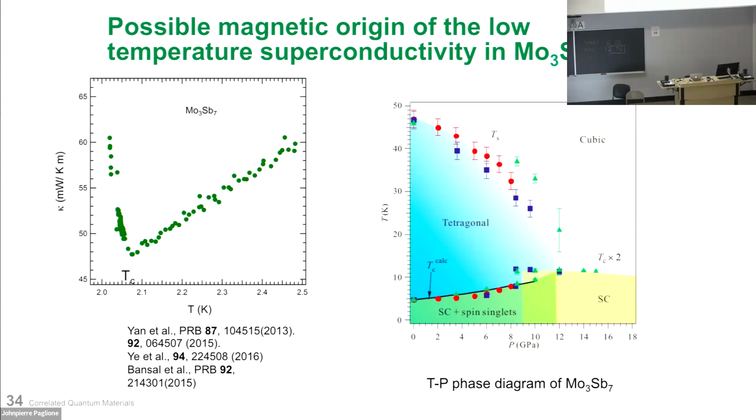So we thought that this was very interesting, and also looked at the phase diagram. There's a structural phase transition, cubic to tetragonal, where in this structure there's molybdenum, which along one direction can dimerize. That's what causes it to become tetragonal, and then it can become a superconductor down here. So this looked vaguely like something that you might see in a cuprate in our case.